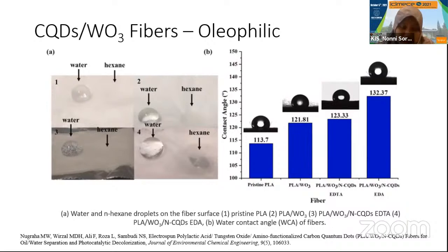So we use polylactic acid as the polymer source, right? When we incorporate these carbon quantum dots and tungsten oxide into the fibers, we can absorb the oil. We can absorb the hydrocarbon into the fiber mats, right? Okay, so how do we form the fiber? We use electrospinning. We mix this material in the solid form, the combination of the carbon quantum dots and tungsten oxide, with the polymer solution, and then we spin it into fiber by using electrospinning.